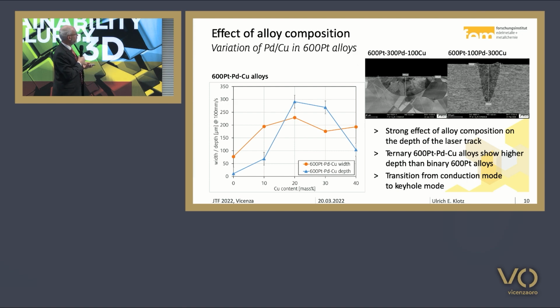If we plot the width and the depth, the blue points are the depth, determined from the metallographic section, and the orange points are the width. We see the width is more or less constant, but the depth is increasing, with a maximum at around 20 to 30% copper in these platinum, copper, palladium alloys.